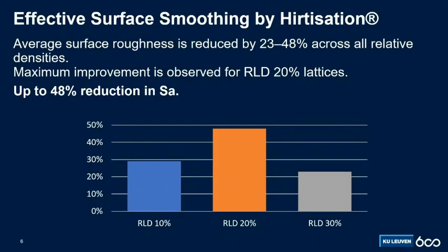Now, this slide shows the average surface roughness reduction expressed as a percentage in those bar plots. And we can see that for the 3 categories of relative lattice densities, we have a span of surface roughness reduction from 23 to 48%, with a maximum, the 48%, almost touching 50%, occurring at the relative lattice density 20%.